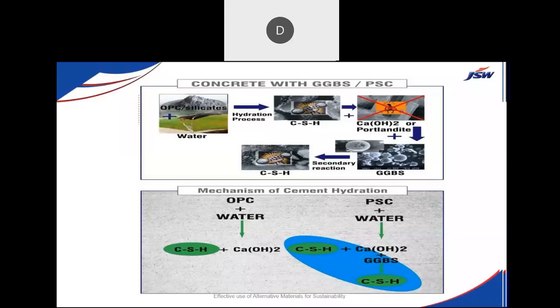Dear friends, GGBS also works like cement when it's mixed with the concrete matrix. So we have water which is added to the cement, and the hydration process will start. We're going to get calcium silicate hydrate gel and calcium hydroxide. This is about 70%, and this is about 30% calcium hydroxide. The combination changes here and there. This is the portlandite in the concrete body. It keeps on absorbing moisture, carbon dioxide, and other harmful chemicals like sulfides and chlorides, and damages the concrete and the reinforcement. So this has a lot of small voids and pores.